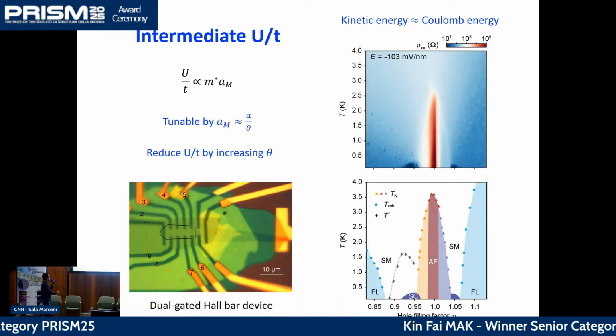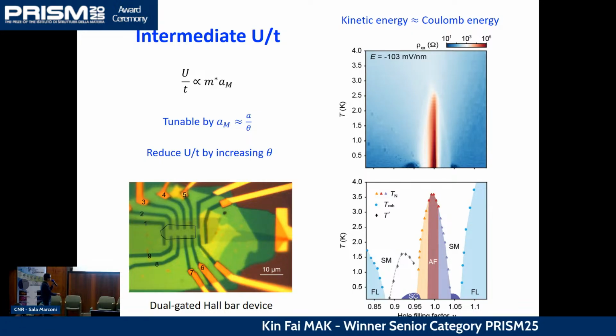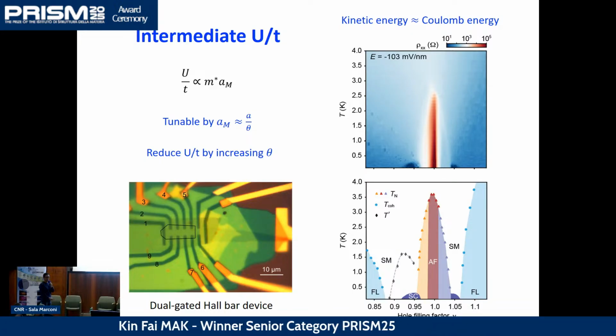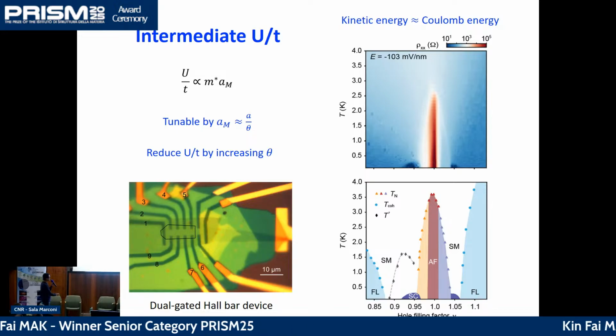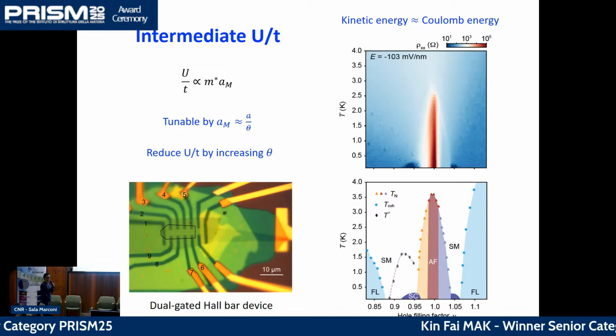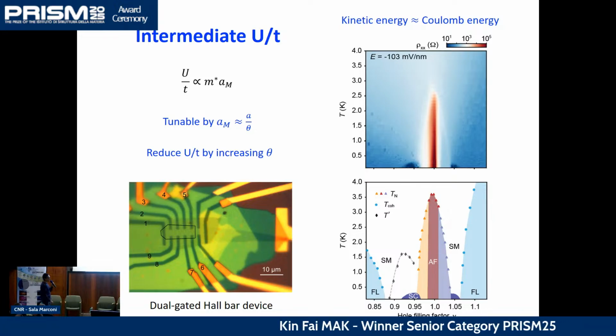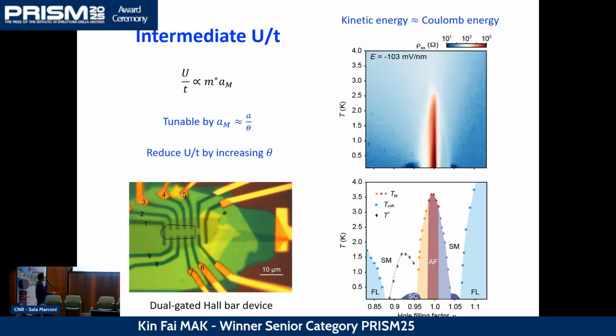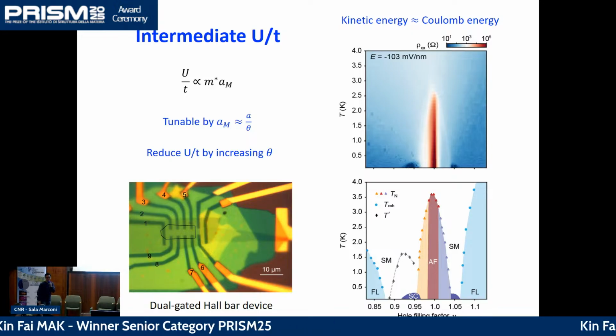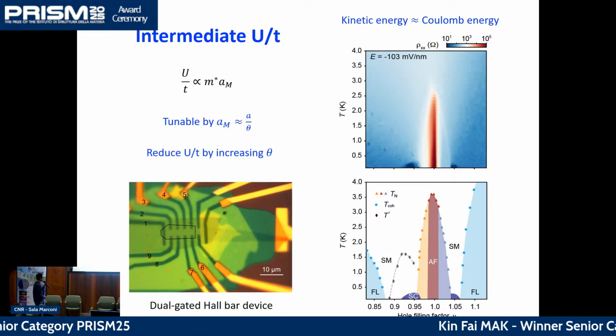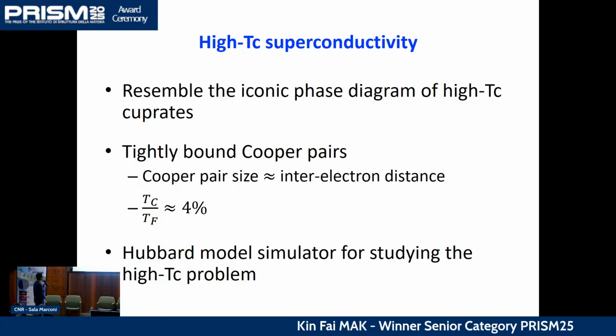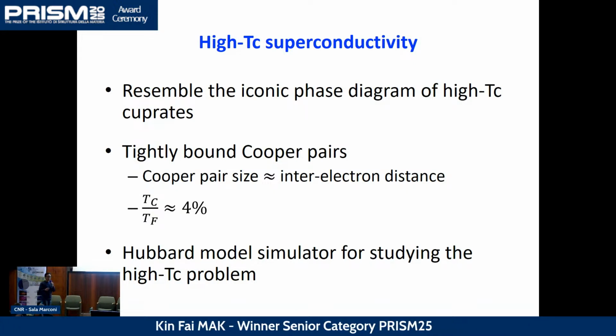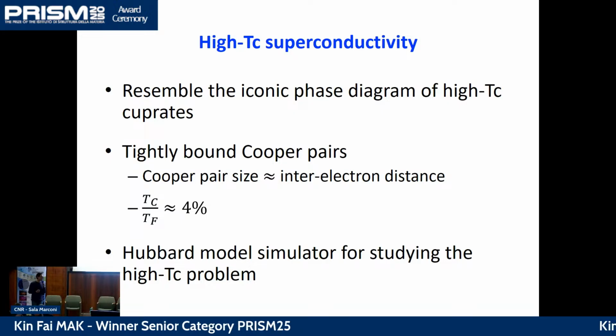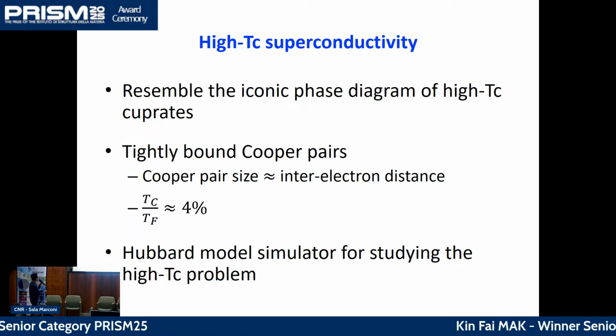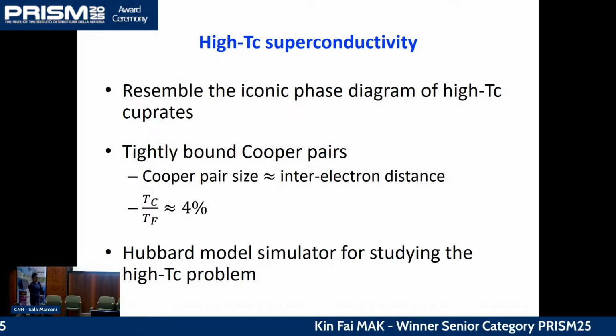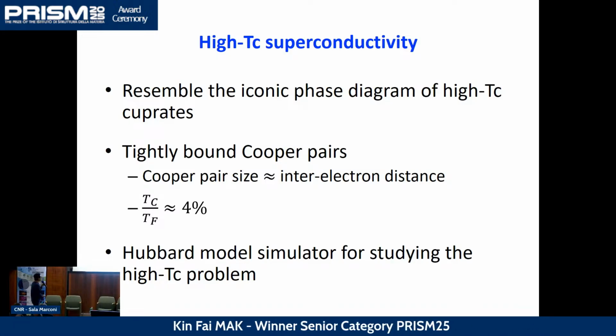So long story short, we have a Mott insulator at half band filling. You dope a little bit away, you kill the antiferromagnetism, and you get 2 superconducting domes coming out that have zero resistivity. And when you dope further away, you recover the usual Fermi liquid behavior. And in this white region here, you actually get strange metal behavior, where the resistivity scales linearly with temperature, okay? Basically, the long story short is that by just making the kinetic energy of the electrons comparable to the repulsive energy of the electrons, we can create a phase diagram that looks pretty much like the high temperature cuprates, if you have looked at it.